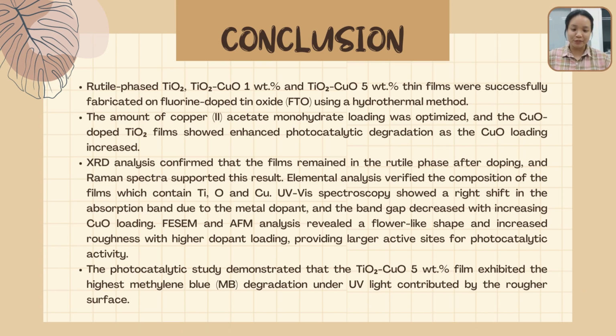To conclude my project, I have successfully achieved all the 3 objectives, and the photocatalytic study demonstrated that the TiO2 CuO 5 weight percentage film exhibits the best methylene blue degradation under 100 watt UV light. And this is contributed by the rougher surface of the sample and also the flower-like structure of the TiO2 CuO film, which helps to provide more active sites for the photocatalytic reaction.